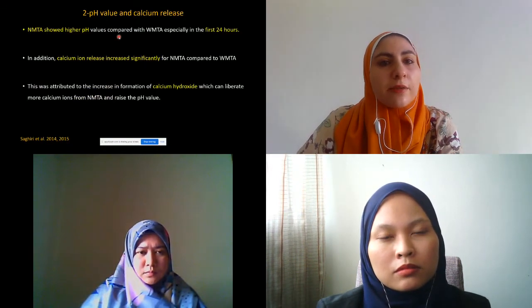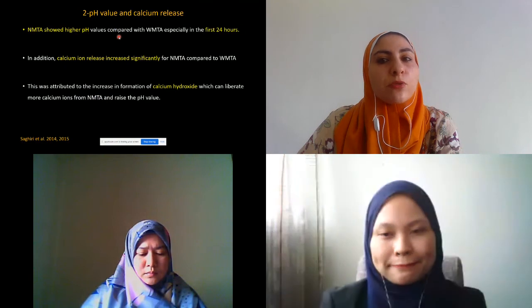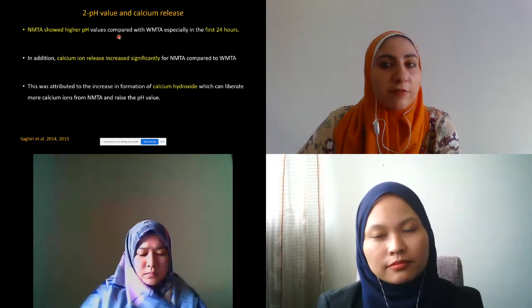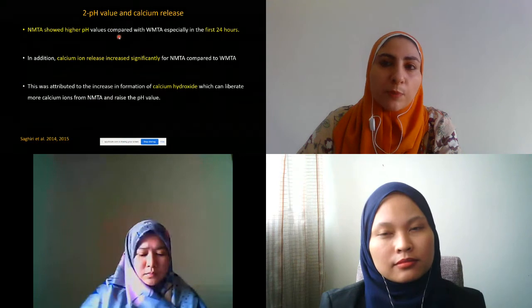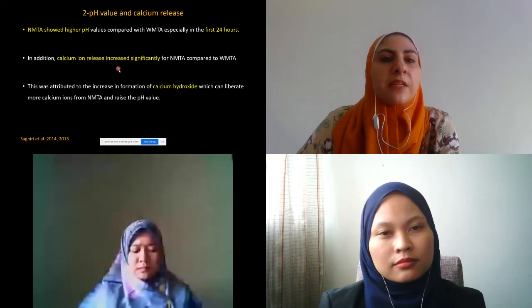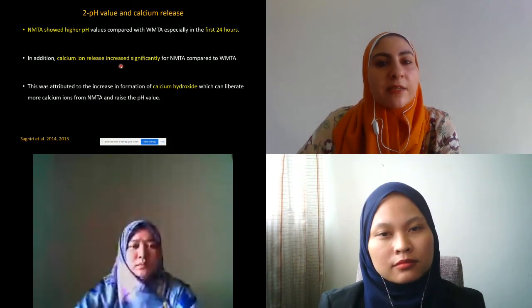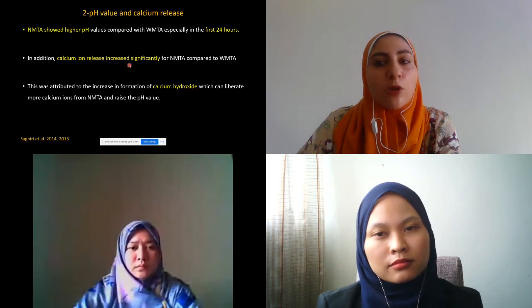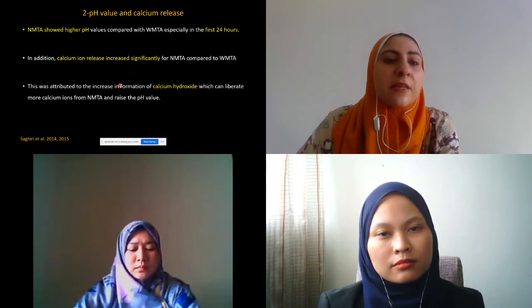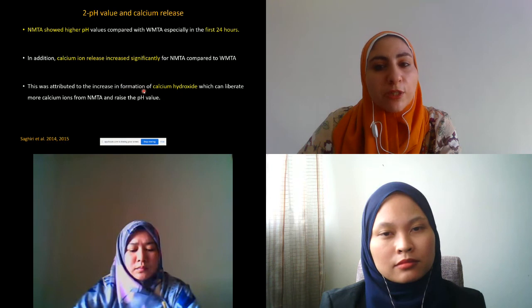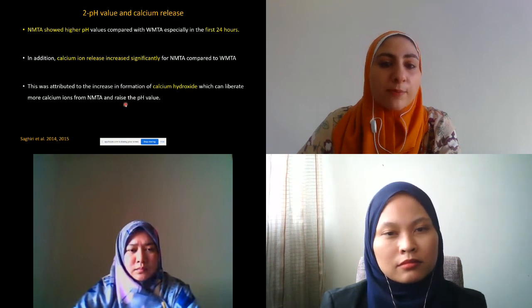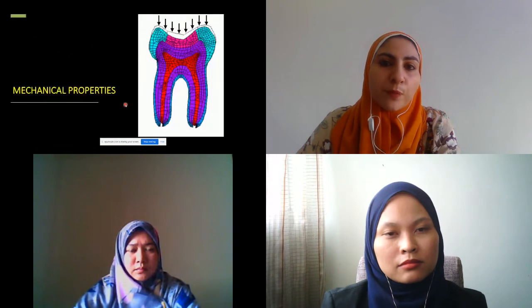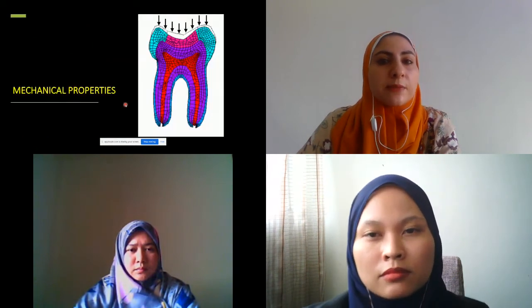Nano-MTA showed higher pH values compared to white MTA, especially in the first 24 hours, which are the most important in dentistry. In addition, calcium ion release increased significantly for Nano-MTA compared to white MTA. This was attributed to the increased formation of calcium hydroxide, which can liberate more calcium ions from Nano-MTA and raise the pH value. Mechanical properties.